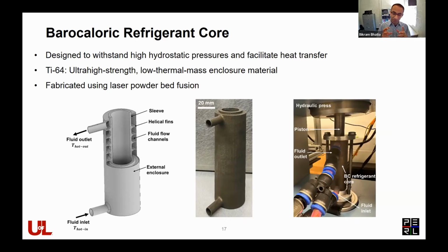Again, the key challenge, remember, is you need to withstand high pressure. So we decided on titanium 64 alloy, which is fairly well known to have really high strength and also has relatively decent thermal conductivity, as a material of choice, which we used to fabricate this barocaloric core using laser powder bed fusion. And the fabricated part is shown here, and the core along with our manifolds are shown here.